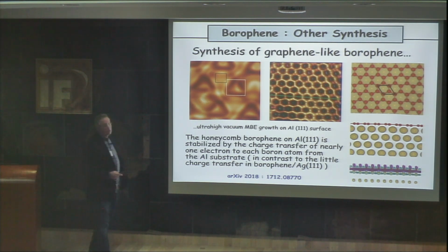But in this case, it's no longer on a silver substrate, but on aluminum. And probably, from calculation, in fact, there is a very strong charge transfer from the aluminum substrate to each boron atom of about 1 electron, which clearly stabilizes the structure. So probably the structure is not really stable when it's isolated out of the substrate. So the main message is that for boron, in contrast, for example, to graphene or other 2D materials, you really have a lot of polymorphism.